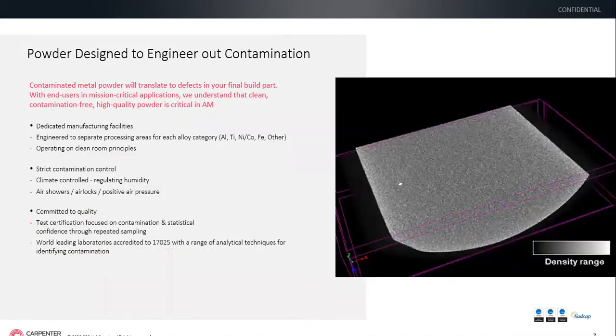If you look at the image on the right, it is essentially a CT scan of a part that is in the process of being manufactured. And the white speck that you see on the image is essentially a high density inclusion. Now, if you have any of these kind of high density inclusions anywhere in your part, in any of the layers, it leads to premature failure. So powder quality is very, very important to enable high quality parts.